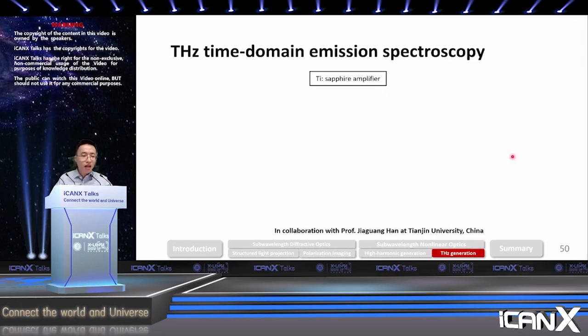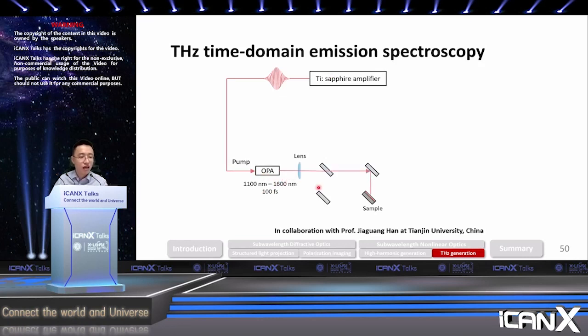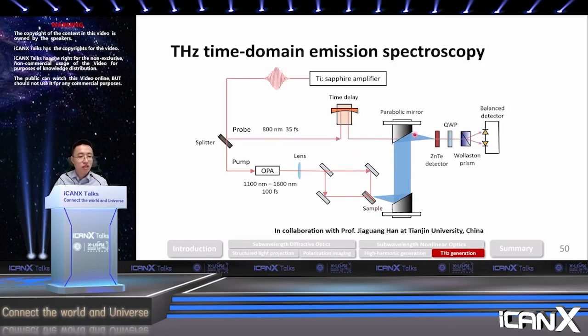Later, in collaboration with Professor Han Jiaguang's group at Tianjin University in China, we built a terahertz time-domain emission spectroscopy setup to see if we can actually generate a terahertz wave from ITO. For the experimental setup, first of all, we have a Ti:sapphire amplifier that pumps an optical parametric amplifier. Then we can shine the laser either on the transmission or the reflection side onto our ITO glass sample. If we can generate some terahertz wave, then we can use a separate probe beam with something called an electro-optic sampling setup.